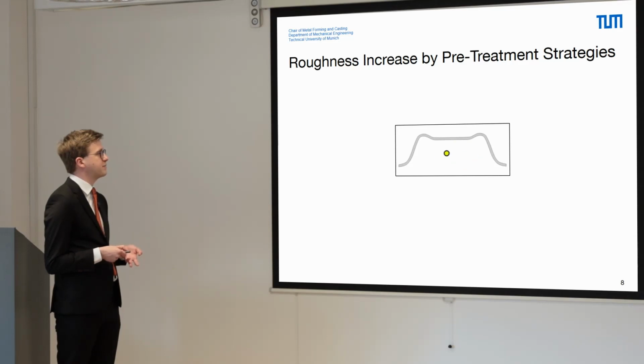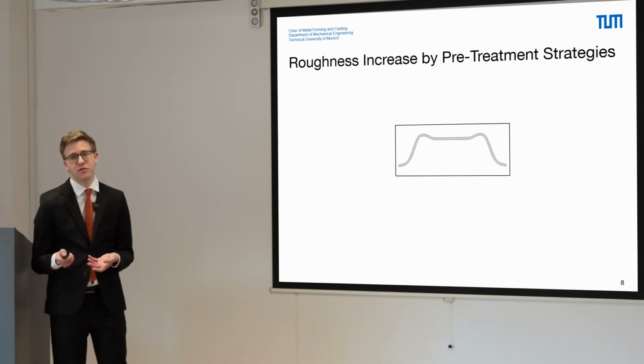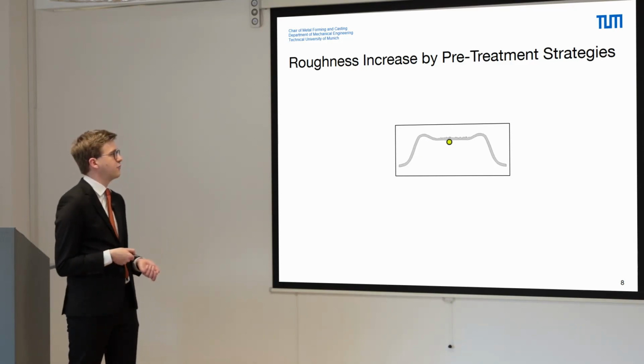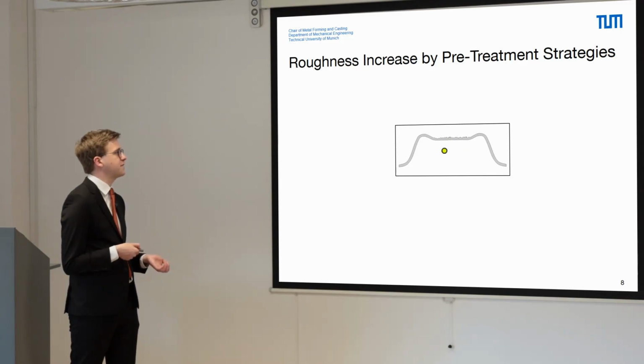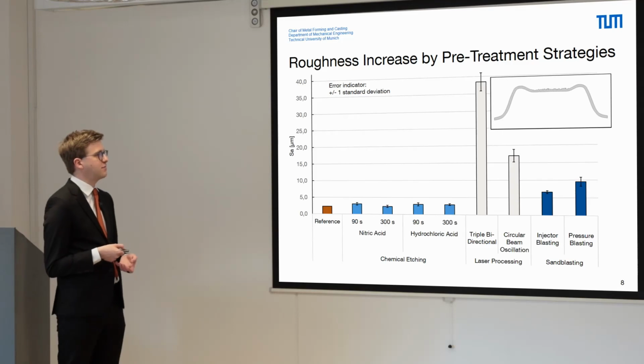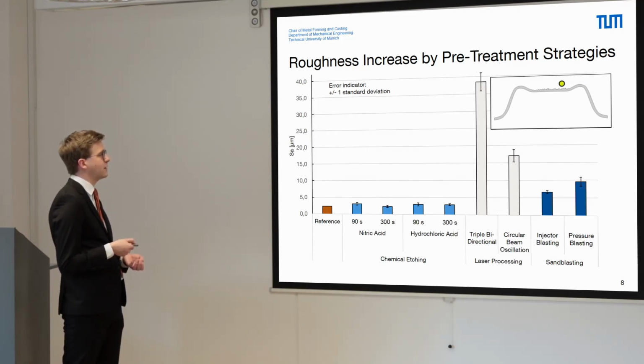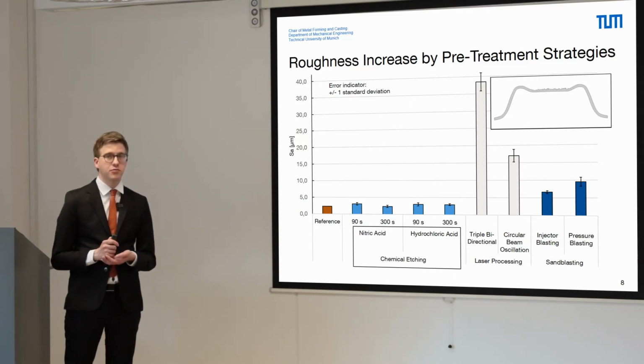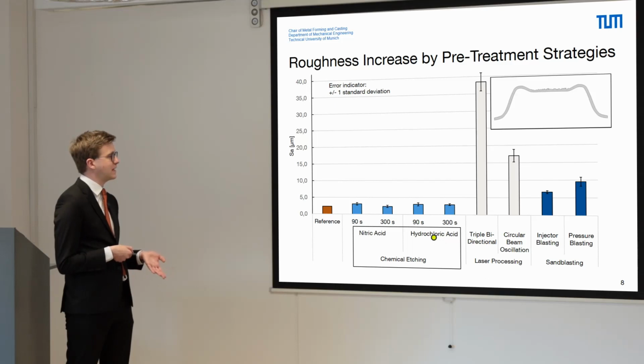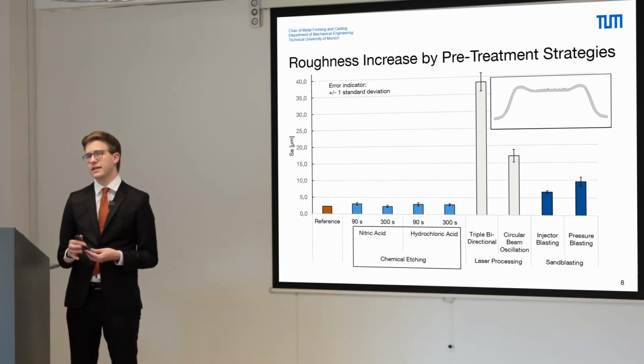After the basic bead geometry has been generated, we can now make preparations for the lamination process. Since mechanical adhesion theory predicts a better bond strength with the UD fibers after the lamination, our goal was to use several pre-treatment strategies which increase the surface roughness in the upper area. As optimization goal, we chose the mean arithmetic height of the roughness in the upper bead area, and as reference we took the untreated sheet geometry, which shows only a very small amount of surface roughness. In the first step, we tried several chemical etching processes using both nitric acid and hydrochloric acid, but none of the etching times of 90 seconds and 300 seconds resulted in a significant increase of the surface roughness.